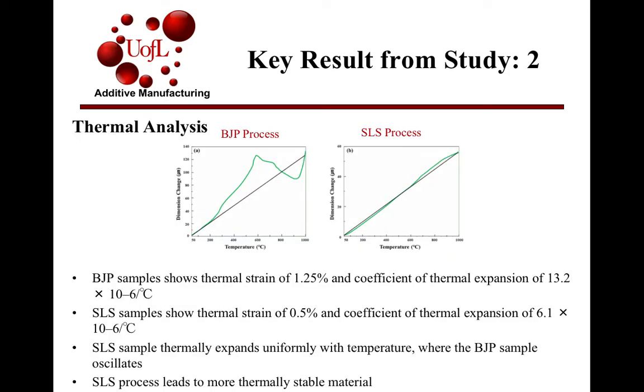The second key result is the thermal analysis. Again, the chart on the left is the BJP process, and the chart on the right is the SLS process. The BJP samples showed a thermal strain of 1.25% and a coefficient of thermal expansion of 13.2 times 10 to the negative 6. The SLS sample showed a thermal strain of about 0.5% and a coefficient of thermal expansion of 6.1 times 10 to the negative 6.